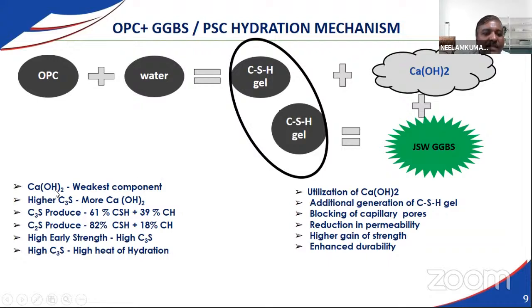So as we are aware, calcium hydroxide is the weakest component, and whenever the content of C3S, the tricalcium silicate, is higher, more calcium hydroxide is generated, and it gives about 61% of CSH gel and 39% of CH. As far as C2S, that is dicalcium silicate, is concerned, 82% of the calcium silicate hydrate gel is produced and about 18% of CH is produced.